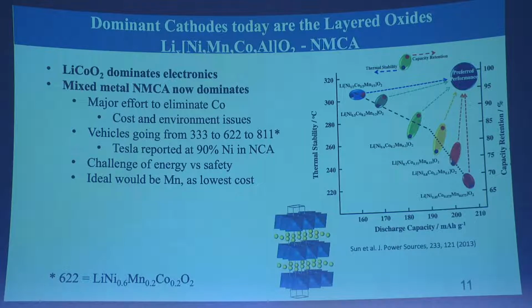So let me talk briefly about what we're trying to do. So on these NMCs, nickel, manganese, cobalt, what we want to do is get the highest energy density we can at the lowest cost. If you look at this plot here, this is a plot from folks in South Korea. The vertical axis is the thermal stability. So if we charge these materials, let's say we take 70% of the lithium out, then we heat them up in the DSC. At some point, they lose oxygen.